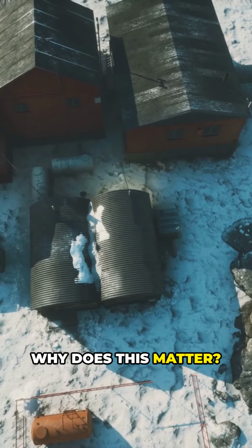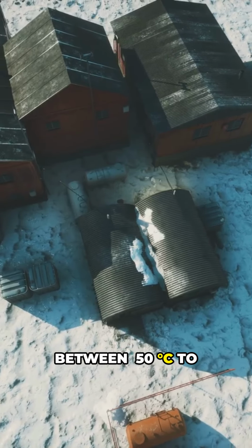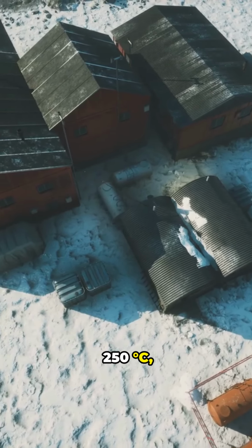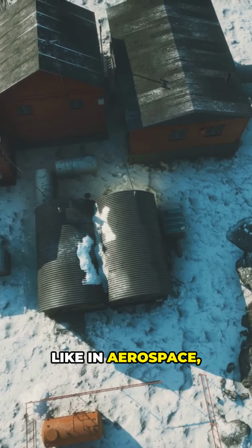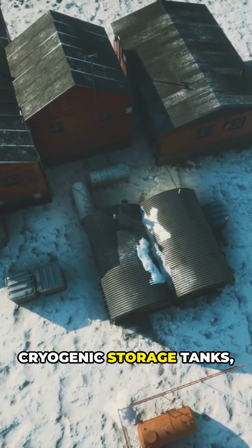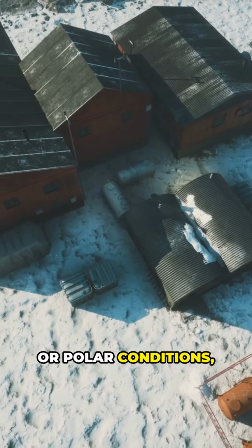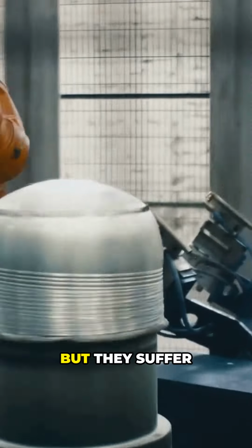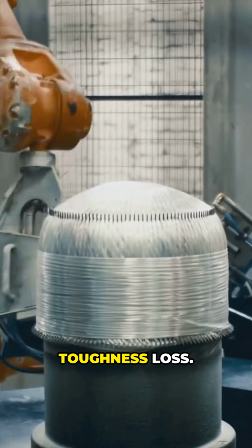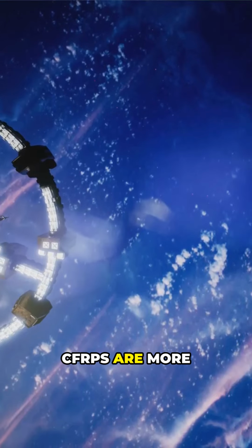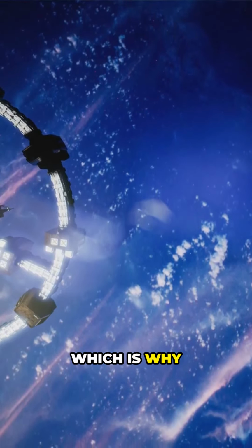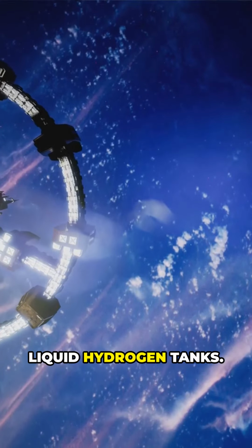Why does this matter? At temperatures between -50 degrees Celsius to -250 degrees Celsius, like in aerospace, satellites, cryogenic storage tanks, or polar conditions, GFRPs are cheaper, but they suffer more from matrix cracking and toughness loss. CFRPs are more reliable in these conditions, which is why they're used in spacecraft and liquid hydrogen tanks.